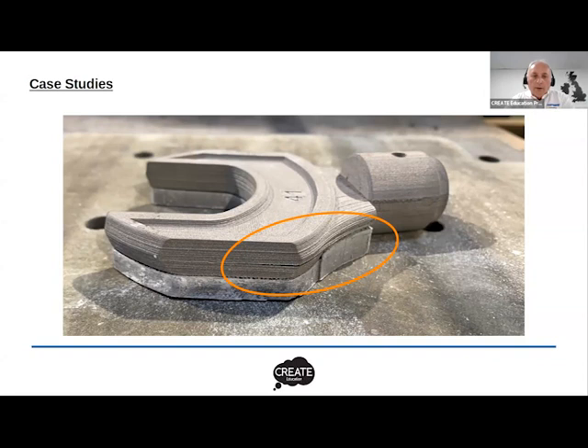But it's a good example of a design that had been designed for CNC machining, not designed for 3D printing. No thought had been given to producing the part using Metal FFF. So it was a good opportunity to step back and think, how would I print that, and what was the reason for this crack? Some of the reason was the thickness of material in that area. There was a lot of thick material there, and that affected the debinding, and that ultimately affected the sintering, and that's when the crack opened up.